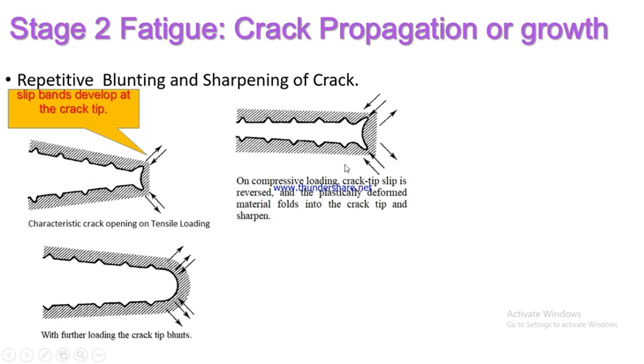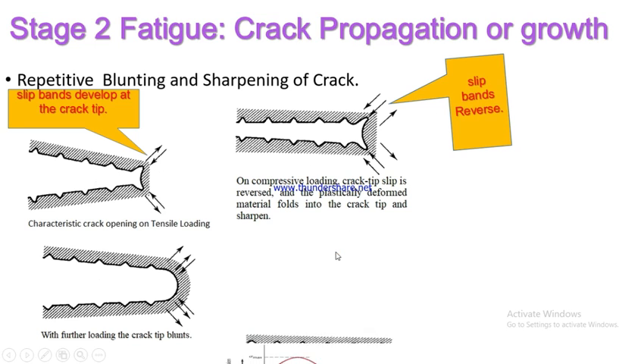And under compression, when you try to compress it again, which has to do with the dynamic loading, you find that the cracks begin to sharpen again, and the slip bands that were projecting from the surface of the cracks will begin to reverse and go back to the surface. All this makes the cracks grow and begin to tear more and more. Then you see the slip bands begin to reverse back again, and those that went in begin to go out.